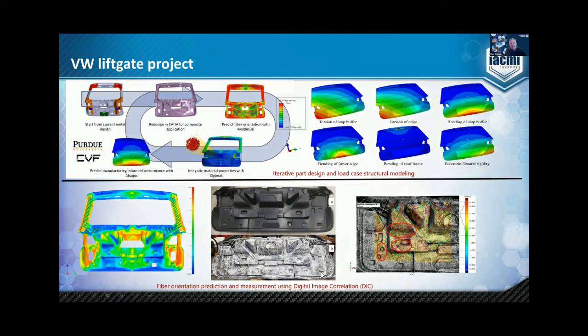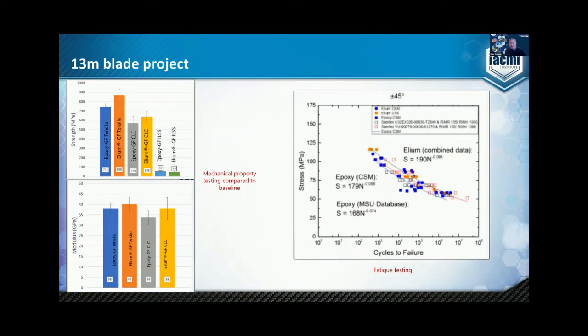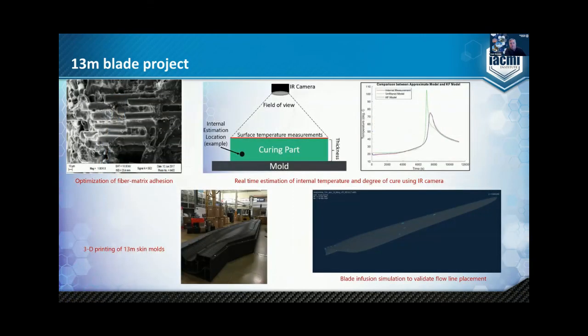And again, digital image correlation was used to validate fiber orientation in that part. On the blade project, early material characterization showed that Elium glass fiber could compete with epoxy glass fiber, both in static testing as well as fatigue testing. We also had some interesting things there.